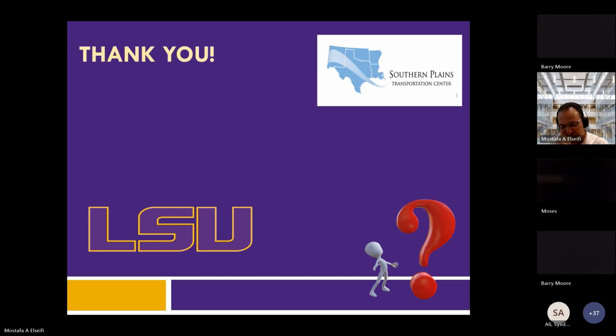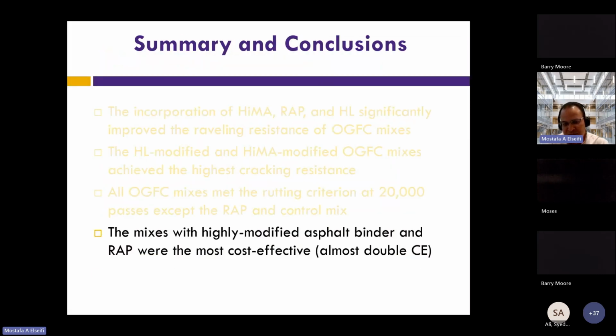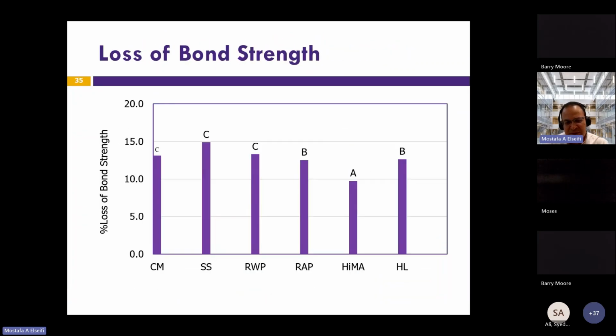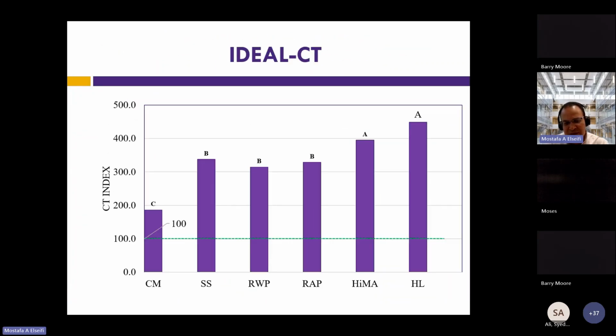So I think that it's possible because the RAP percentage was slightly lower than what is currently used for other types of mix. So if we go back, the RAP percentage was only 7%. So again, that's a factor to consider. And recycling waste plastic also depends on the source of plastic that you use. I know that the majority of studies that do recycling waste plastic grind the plastic to maybe filler size, and also mix it with the binder.